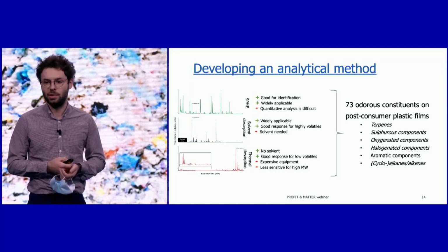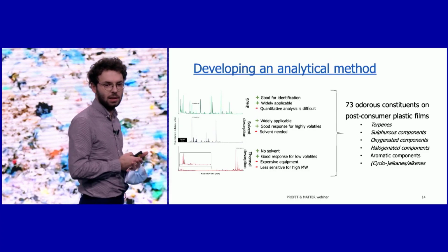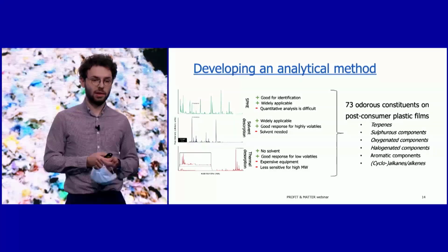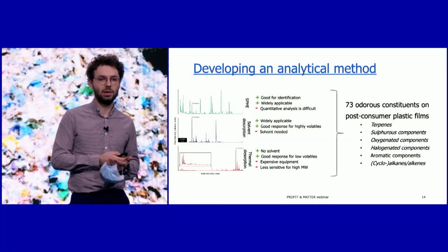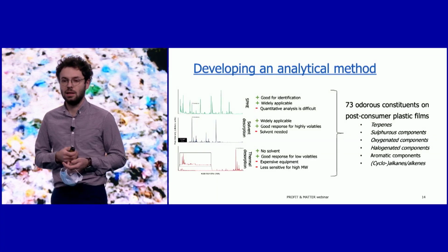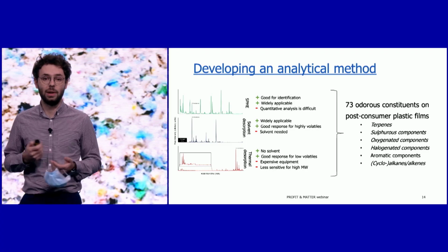For the thermal desorption method, no solvent is needed, and a quite good response for the high volatile components was achieved. But the disadvantage here is that it was less sensitive for the high molecular weight components.